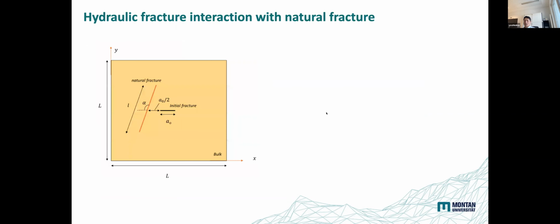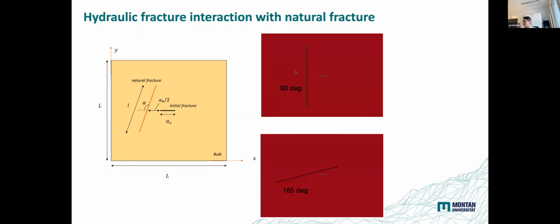Okay. All right. So I just have one more example that I would like to show, and this is about hydrofracturing. Here in 2D, I simulated the hydraulic fracture interaction with a natural fracture. I placed some initial fracture, and then I placed a natural fracture some distance away from this initial fracture with some angle. So I simulated two cases. One is the 90-degree case, and the other one is the 165-degree case. This black line represents the natural fracture. The natural fracture is represented with reduced fracture toughness. So this is some weak material in this black part.